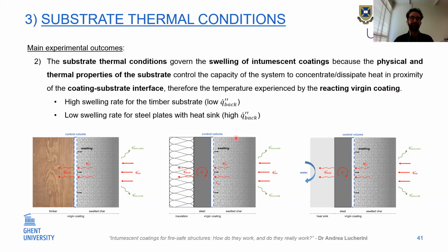is experiencing. So in the case of an insulated steel plate, you can imagine that the heat penetrates through the coating and starts collecting in the plate, and the temperature starts increasing based on the thermal inertia of my steel plate. In the case that I have a heat sink cooled by water, you can see that heat penetrates, reaches the steel plate, but is also cooled at the back.